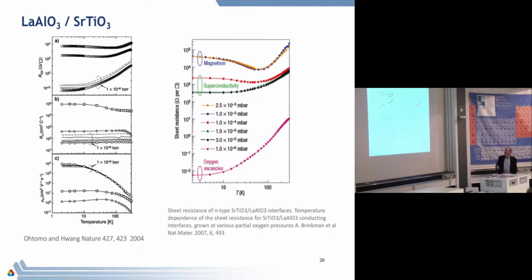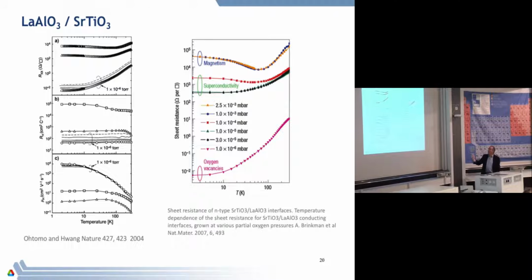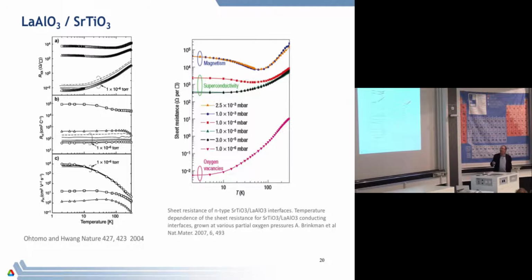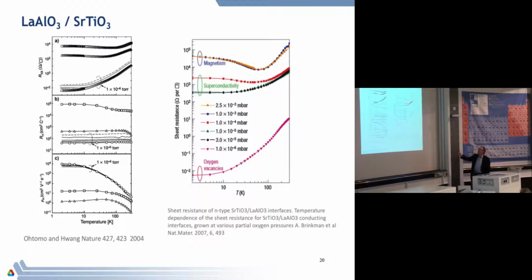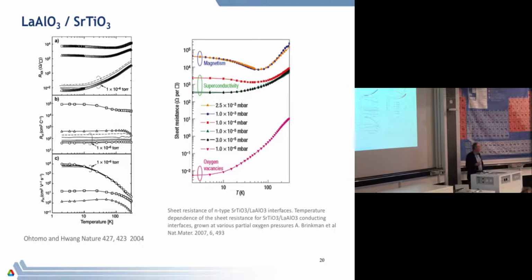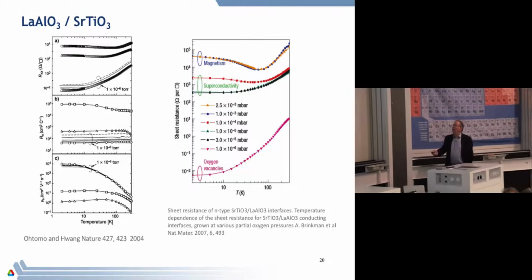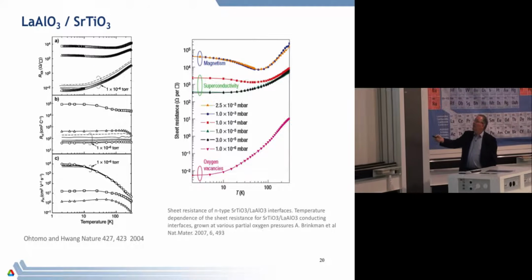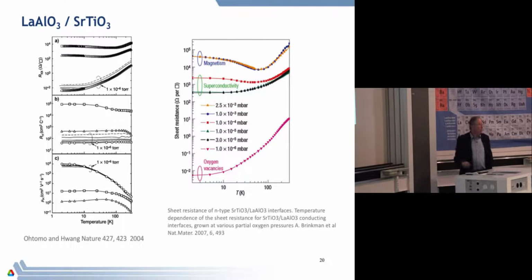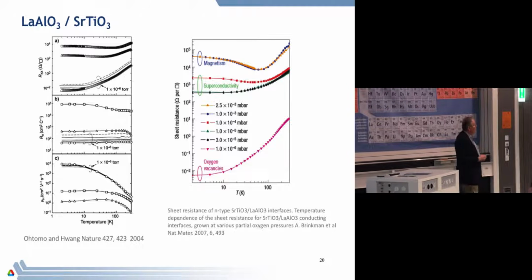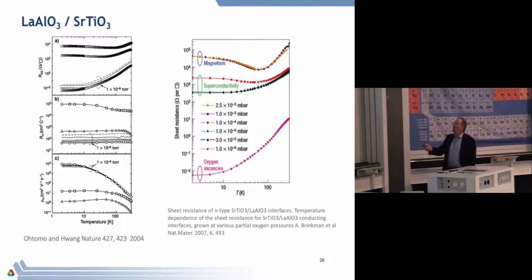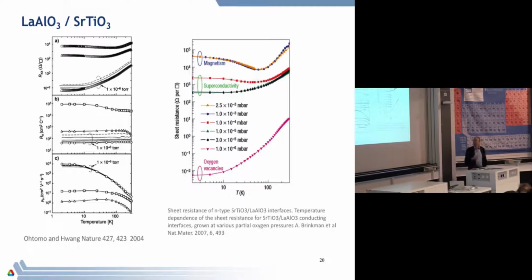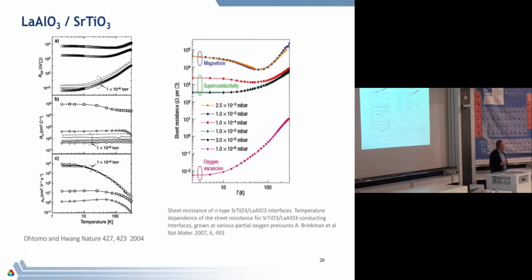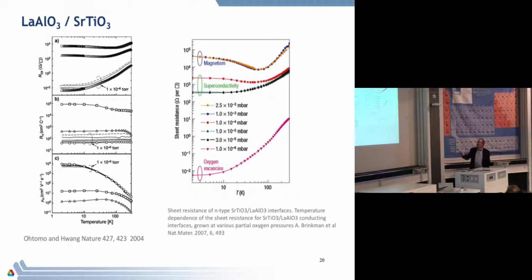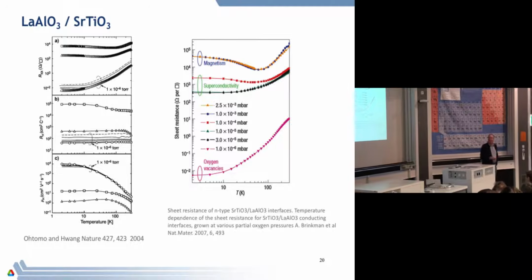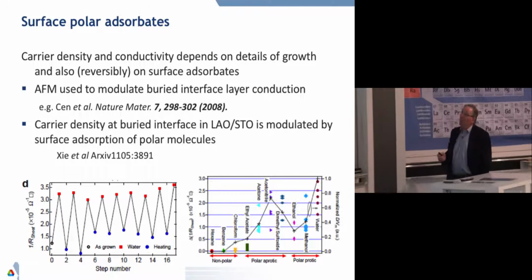Okay. I don't want to go into the discussion of magnetism and superconductivity, the resistivity measurement here, but just to notice that what happened in this experiment is that the answer you got depended on the pressure of the oxygen at which you grew the material. If you grow at very low overpressures of oxygen, you create a lot of oxygen vacancies. Oxygen vacancies add carriers to the material, and they dope it. Okay? As you make the system closer and closer to the stoichiometry, you get less and less of that physics, but you see that you've already implicated something very different about the way that this might work. And let me give you a thought about how that would happen.